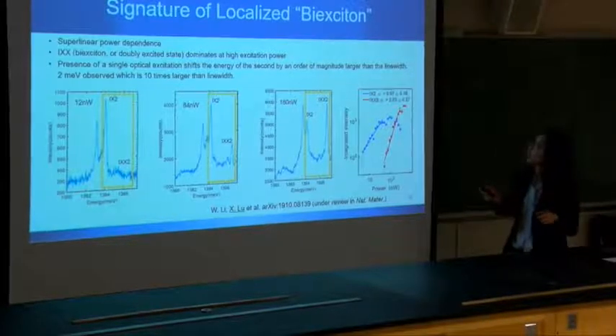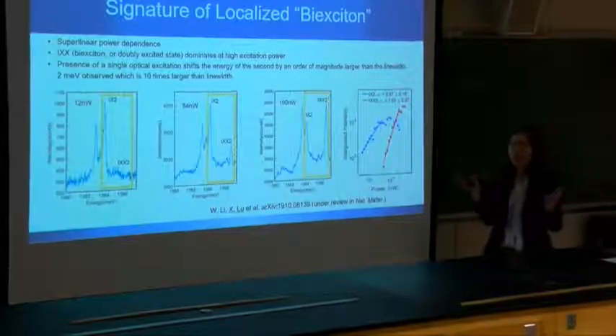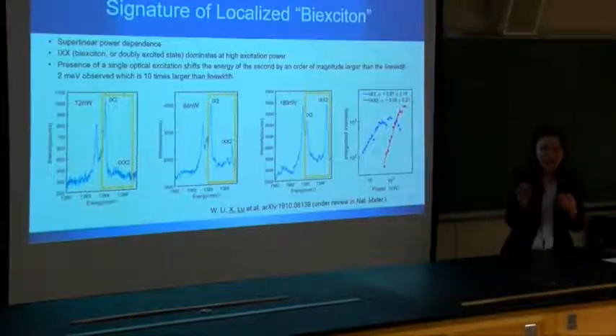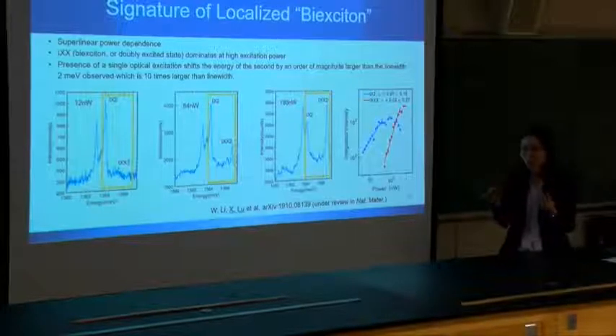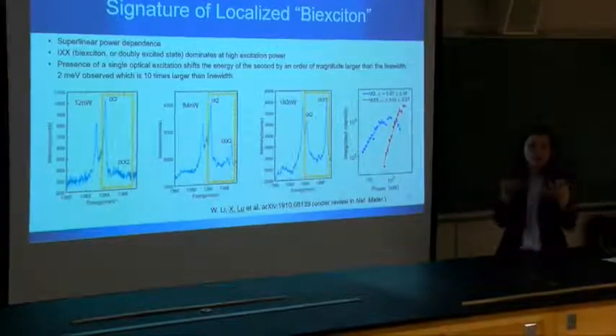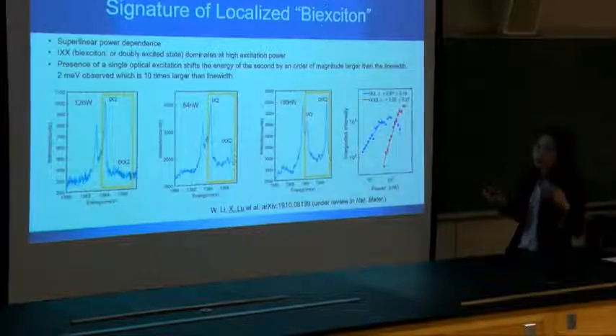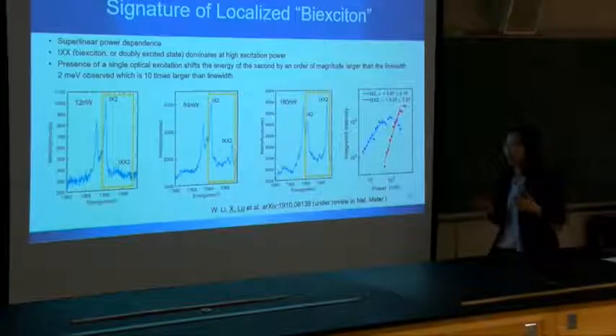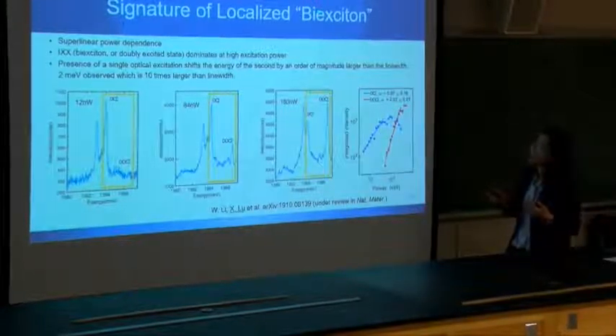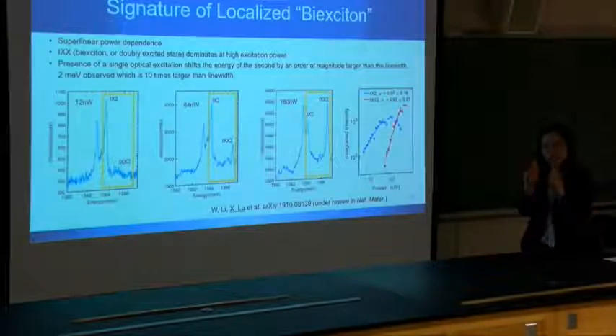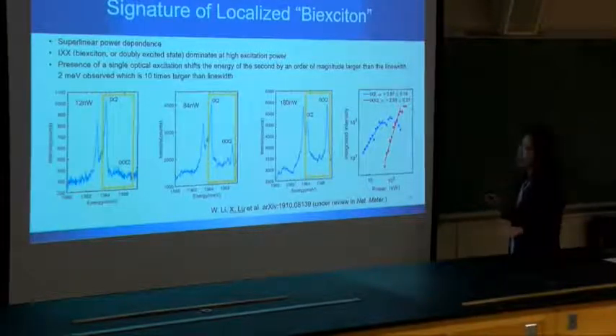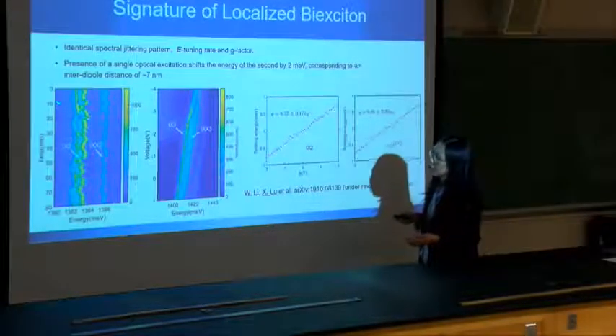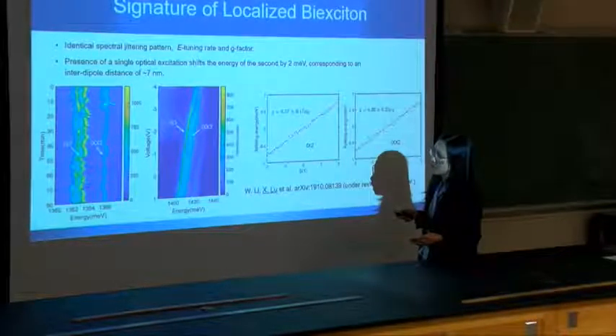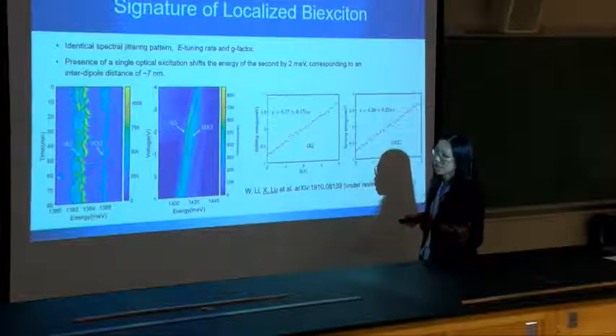So here we use the word bi-exciton, but I need to clarify it, because usually in semiconductors, people would think that bi-exciton is a bound state, which means that it will lower the energy if it forms a bi-exciton. But in fact here, for the bi-exciton state you need to pay more energy because of the dipole. But we still use the word bi-exciton because these two states are related, although you need to pay more energy. So here is the time trace, and we see that the single excited state, or the exciton state, and the bi-exciton state have the same jittering pattern because they're in the same potential well. They see the same local fluctuation.